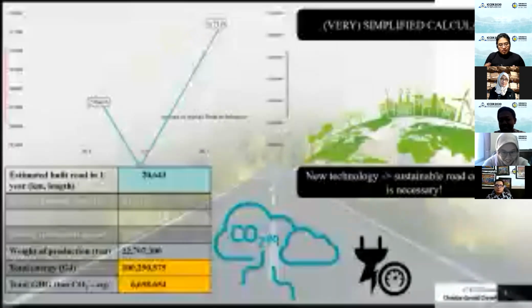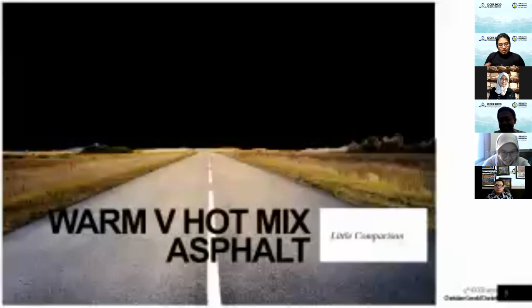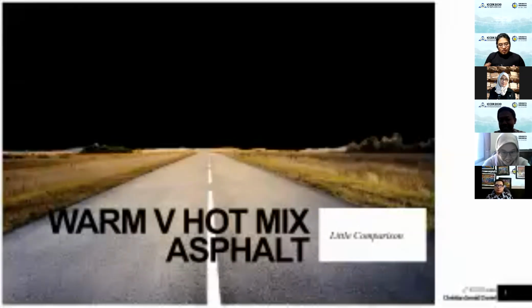One of the approaches is to perform warm mix asphalt, which is basically the normal one, but produced at a lower temperature of 100 to 140 degrees Celsius. Several benefits are to reduce fuel consumption, reduce energy consumption, and also to create a better health exposure for the worker because of the less heat and the less emission of carbon dioxide. We also have a longer window of compaction. We can compact more in a day, basically.